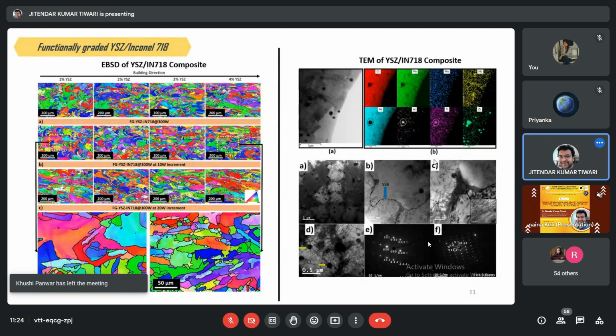Yttria is used for the stabilization of zirconia, and up to 8% the zirconia will fully stabilize. We call it fully stabilized zirconia. Basically we are adding yttria to arrest the transformation in zirconia, because a transformation occurs when we heat simple zirconia; the crystal structure of zirconia changes. After the addition of yttria, the tetragonal structure of the zirconia is stabilized. That's why we call it yttria stabilized zirconia, and here you can see the distribution of zirconia.